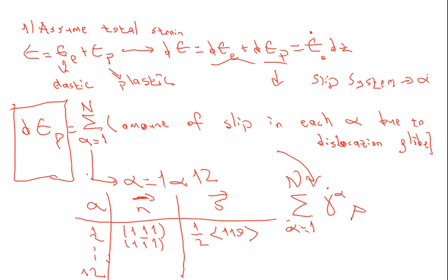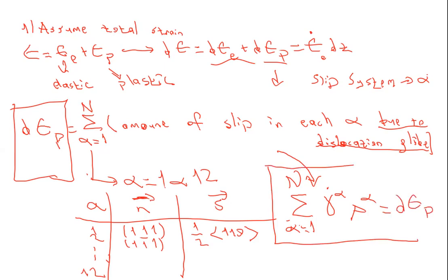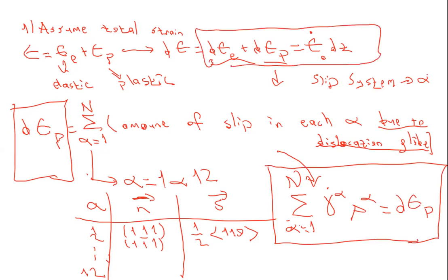And due to the dislocation glide, so dislocation density corresponds to dislocation glide. So this is the formula. This is the important formula for d epsilon p. Remember, we're going to calculate this one, and we are trying to find d epsilon p, which is just shear rate times the dislocation density. And how can we calculate the shear rate?